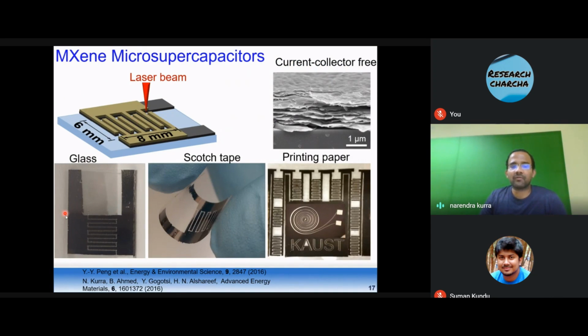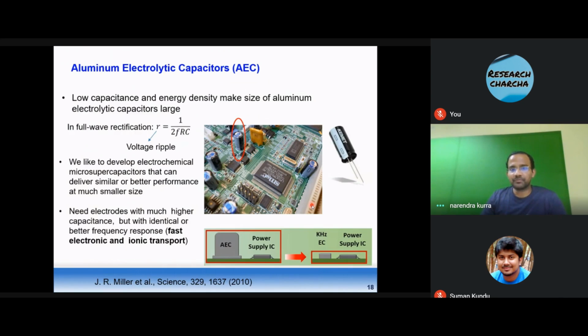And we can fabricate devices on a glass substrate, as well as transfer onto flexible Scotch tape. Even one can make devices on printing paper surfaces, and so on. But one of the key applications of MXenes, because of their high conductivity and excellent charge storage properties, is in electronic circuitry, to remove the ripples produced in an electronic circuit in ICs, integrated chips. So this is a bulky electrolytic capacitor, as you can see here. This is one of the bulkiest components sitting in the circuit board. It has a low energy density. If we can make a supercapacitor that operates at high frequencies, one can get rid of this bulky capacitor. This is where one of the key applications of micro supercapacitors fits in.